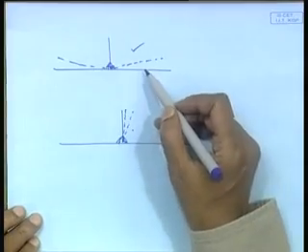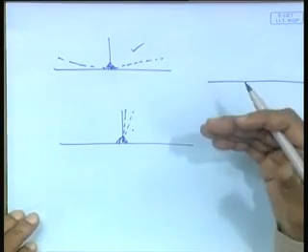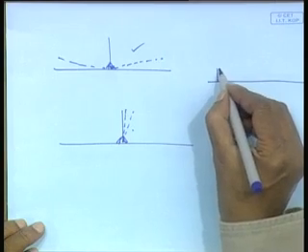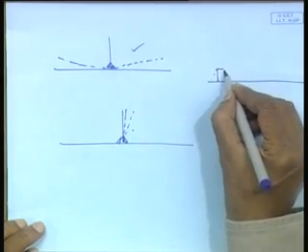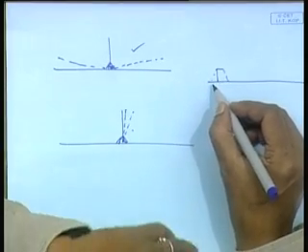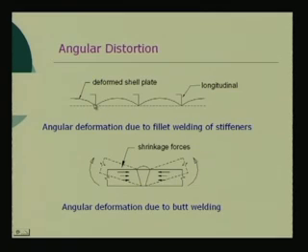Now what happens is, instead of this, this frequently happens, the first one, the plate deforms. Why? Because when a stiffened panel is fabricated, how do you fabricate? Say we put a stiffener. The stiffener is held in position by means of supports. It is not allowed to move this way, that way. The stiffener is held in position, but the edge of the plate is free. So it deforms. That is what is here. It is lifting up, deforming, right? Both the edges, as I am welding, the plate is lifting up,